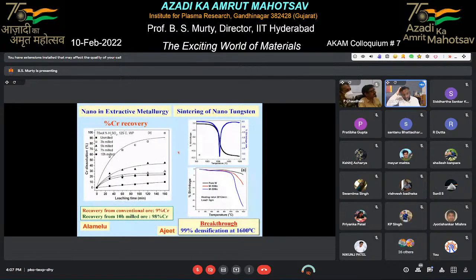People also started seeing that this kind of nanotechnology has significant advantages in various ways. For example, I can take these nanoparticles and sinter them at very low temperatures. Many of you know tungsten is used as filaments in bulbs, and we also use tungsten as kinetic energy penetrators in defense. But unfortunately, tungsten has a very high melting point, 3400 degrees. If you want to sinter tungsten powder, you need to sinter at 2800 degrees centigrade. Whereas we have made nano tungsten by simply taking the commercially available tungsten powder and ball milling it for just about 3 hours. You get a nano tungsten, and that nano tungsten can give you close to 100% density at 1600 degrees centigrade. You are able to save a lot of energy by sintering at low temperatures.